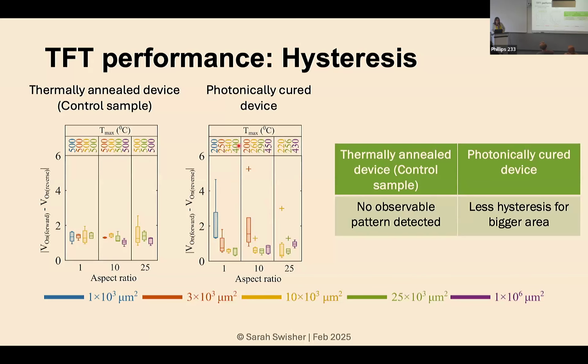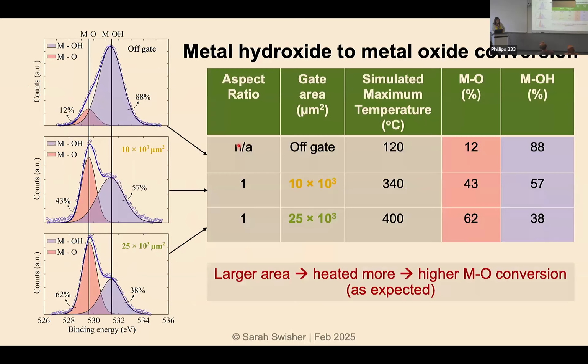So all the transistor characteristics line up with our simulation. And then we also looked at the XPS, so this conversion of the sol-gels to the metal oxide. I included here a point that was measured off of a gate. So this would be a region where there is no metal underneath the semiconductor, but it's still cured, right? It's still hit with the flash lamp. And as you can see, there is almost no conversion here at all.